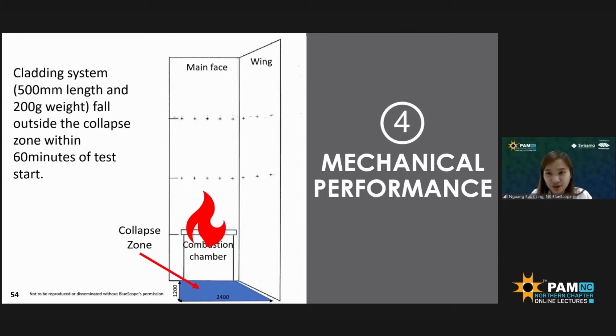So for the fourth criteria, there should not be any component of the cladding that is longer than 500 millimeters in length and 200 grams in weight, meaning that the object shouldn't fall outside the confined space. Otherwise, it will create a roadside safety hazard or even affect the firefighters' effectiveness in putting out the fires. So if any object is found to have fallen outside the collapse zone within the 60 minutes from the start of the test, then it will fail this criteria.